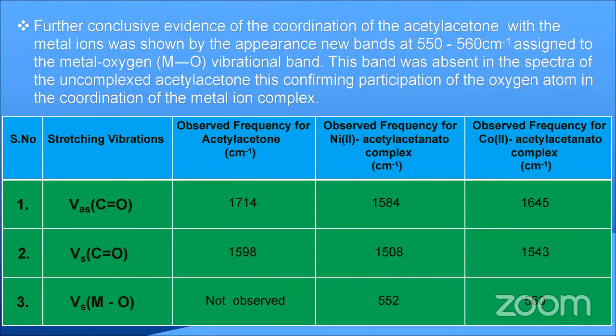From that, another stretching frequency can be observed in nickel and cobalt due to the stretching vibration between the metal and the oxygen of the carbonyl group of acetylacetone, which is at 552 centimeter inverse in nickel and 560 centimeter inverse in cobalt. This band is absent in the uncomplexed acetylacetone, confirming the participation of the oxygen atom in coordination of the metal ion complex.